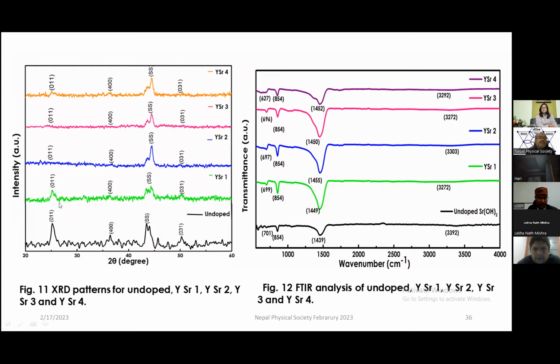As you are doping here, one can also see that, compared to the previous one where there were sharp peaks, the peak intensity is also going to decrease. The peaks are decreasing. It has been observed that amorphous nature gives better supercapacitor behavior than the crystalline one. So it is moving towards that, which is very good. XRD is needed to see this statement exactly, but roughly that is what we have observed.